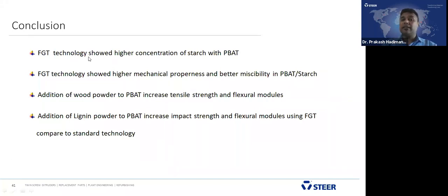Finally, we conclude that FGT technology showed higher starch addition with PBAT. Starch goes up to 80% addition with just 20% PBAT. This did not happen in the standard technology, which stopped at 50-50, only 50% starch. FGT provides almost 80% starch addition, higher mechanical properties, and better miscibility of PBAT and starch in the final compound. FGT also showed higher mechanical properties in most cases compared to the standard technology. The addition of wood powder and lignin powder increases tensile strength, flexural modulus and impact strength. Lignin powder with PBAT increases impact and flexural modulus using FGT compared with the standard technology.